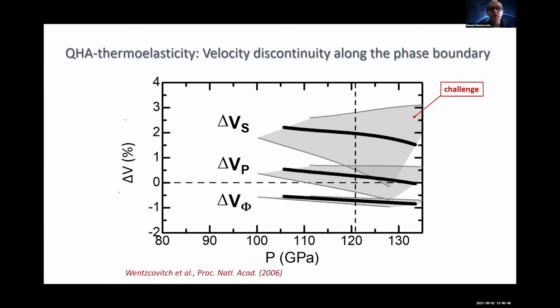Delta VS 2%, in the mantle 1.7% in a cold region beneath the Caribbean, where we expect to see this transition. Delta VP 0.5%, in the mantle 0.75%. So this was very surprising and rewarding and puzzling. The lower mantle is certainly much more complicated than the simple transition we investigated, but this feature must be robust. And that's why we're able to reproduce it. But there must also be some fortuitous agreement here. For some wrong reason, we are agreeing with respect to transition pressures, etc.